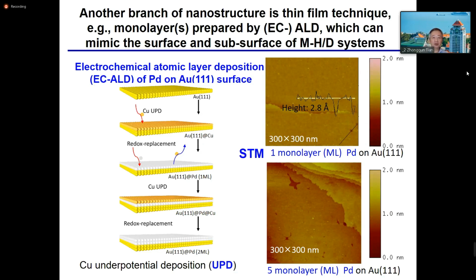Because we think another branch of nanostructure is not the three-dimensional nanoparticle, but thin film, ultrathin film, with maybe one to a few monolayers, or to a few tens of monolayers. It can be prepared in several ways, especially by atomic layer deposition. There is a small branch of ALD using an electrochemical deposition way. For example, this is a gold 111 surface, so we can utilize underpotential deposition of copper to get one monolayer of copper. Then we can do a chemical reaction, redox replacement. We add some palladium ions, so it can replace copper with palladium.